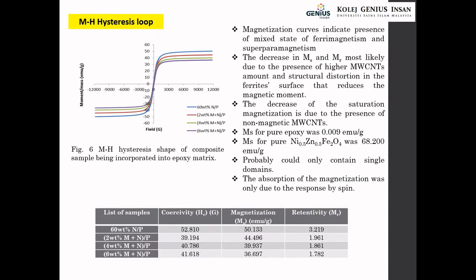For the MH hysteresis loop, the magnetization curves indicate the presence of a mixed state of ferromagnetism and superparamagnetism. Ferromagnetism comes from the sigmoid shape and the coercivity, whereas superparamagnetism is due to the smaller grain size. You can see from the table here the coercivity value, saturation magnetization value, and retentivity.